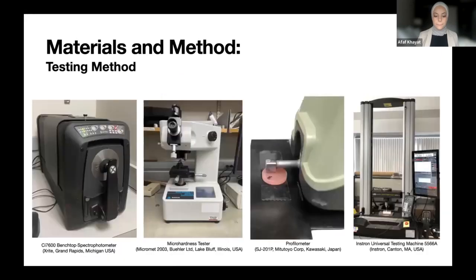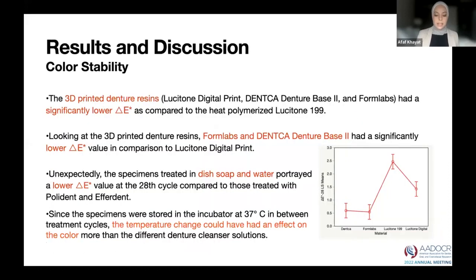The color stability, micro hardness, and surface roughness testing was done at intervals at baseline, 8th, 16th, and 28th cycles. Biaxial flexural strength testing was done at baseline and the 28th cycle. Statistical analysis was done using the Tukey HSD test with a significance level of 0.05. Statistical analysis was done with the JMP Pro software.